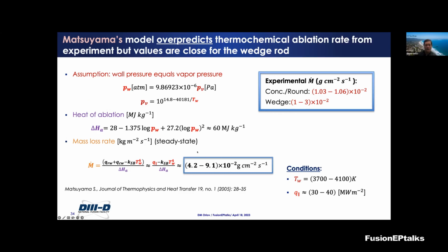If you look at these numbers that Matsuyama's model was predicting, and the numbers that we measured experimentally, his numbers are definitely overestimating what we had. They're a bit close to the wedge case, but still somewhat above it.